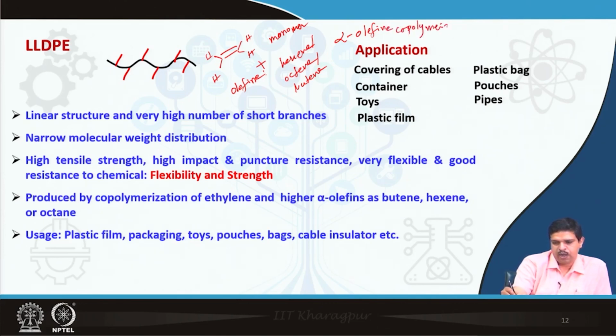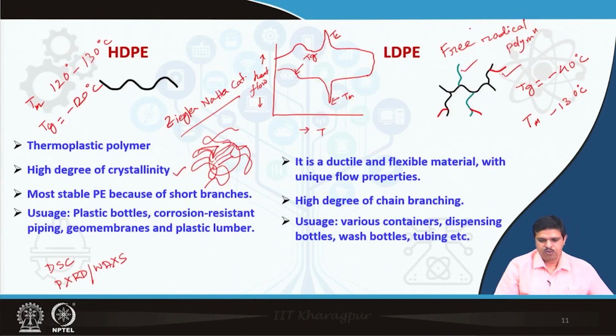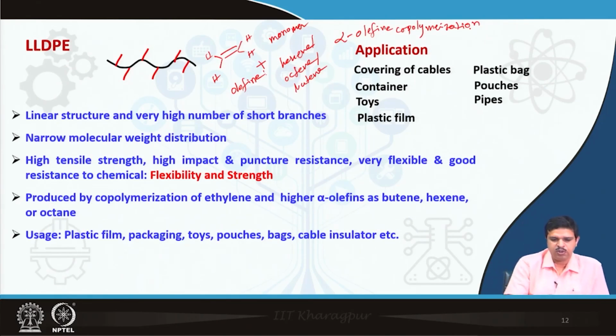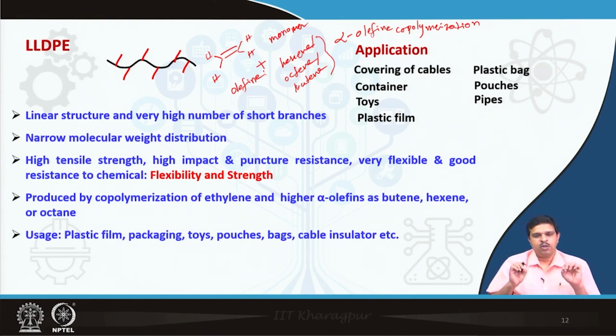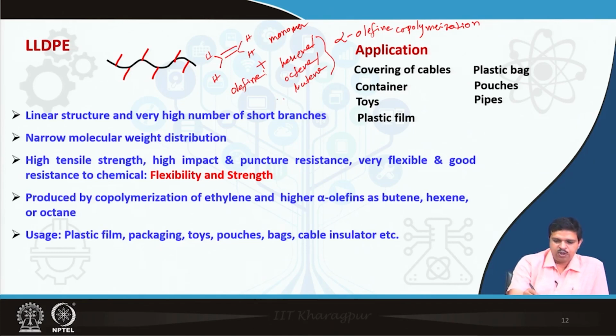So, in this case we use only one monomer, that is ethylene, but in this LLDPE we use ethylene and also another monomer, hexene olefin or butene. These are the alpha olefins. So, depending upon the ratio, how much we are feeding, the number of the small branch chains will be varied. So, this is a very well defined low density polyethylene, which is basically linear low density polyethylene. And this kind of polymerization protocol is quite recent.